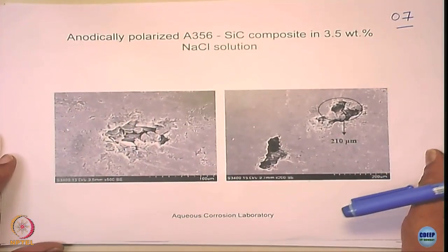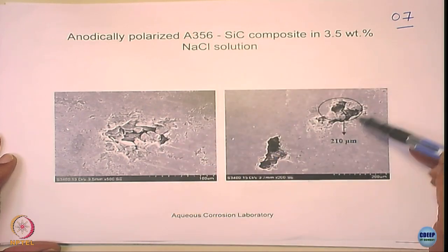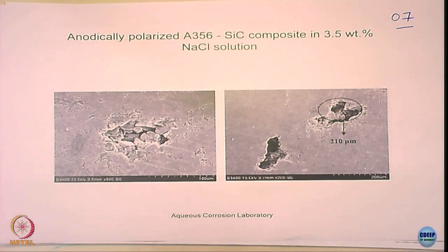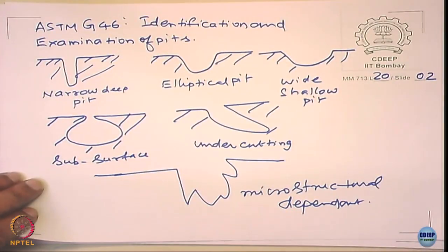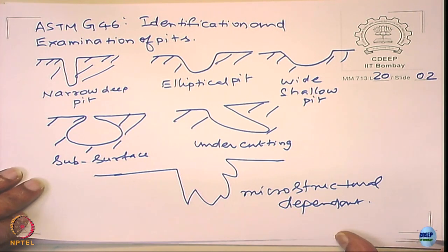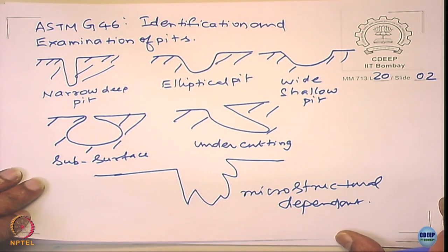You can see here pits taking the morphology of silicon carbide composites — the shape of the composites is followed. So it can take all kinds of complex shapes. You can have nice hemispherical pits or complex shaped pits depending upon the alloy, because the alloy is not homogeneous; it can be chemically heterogeneous, leading to uneven pit corrosion morphologies.